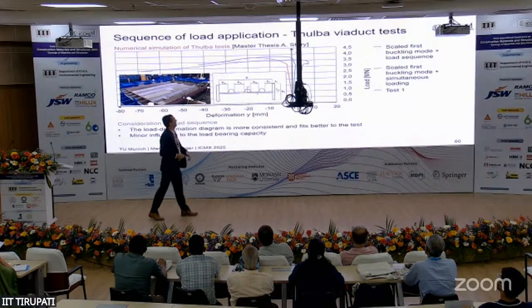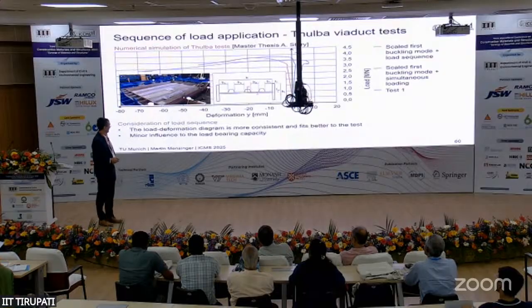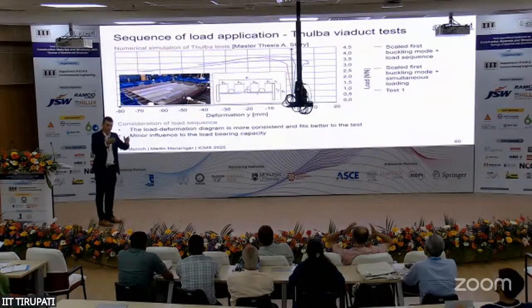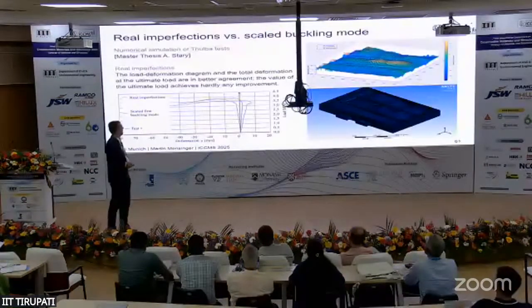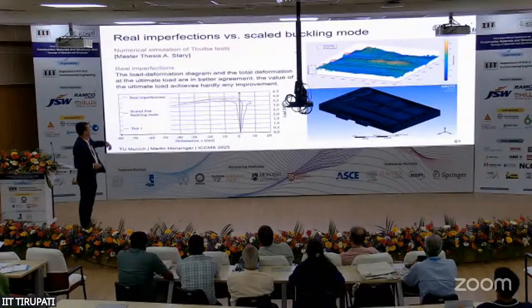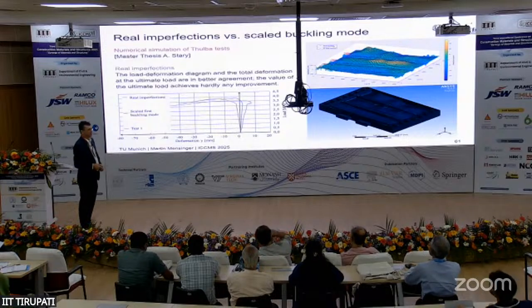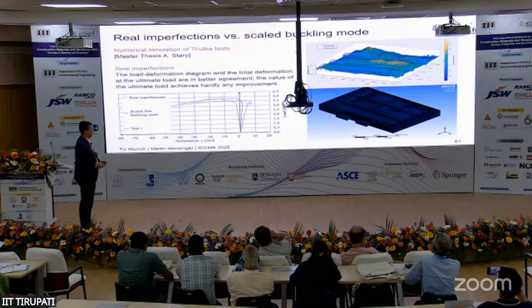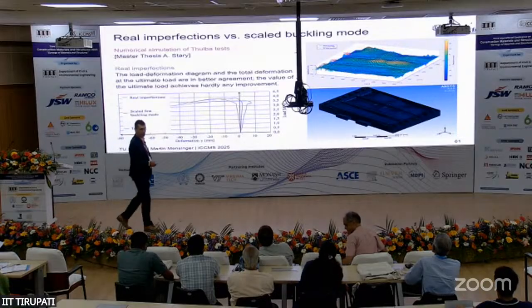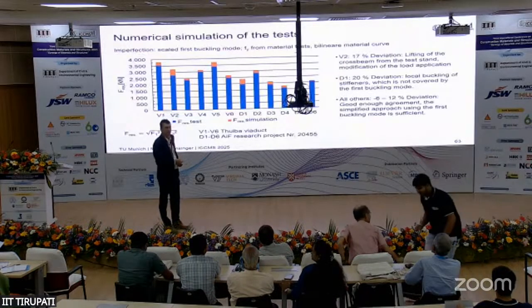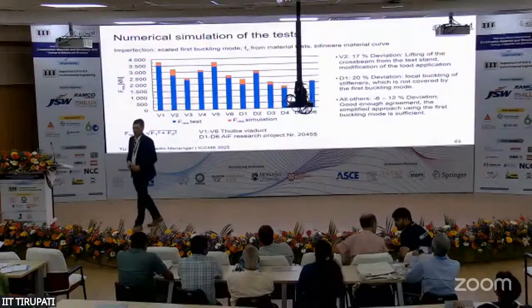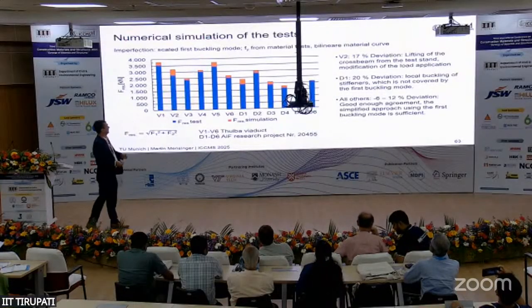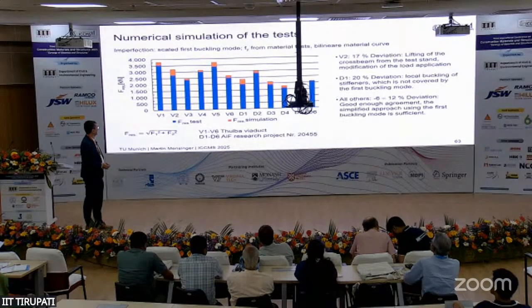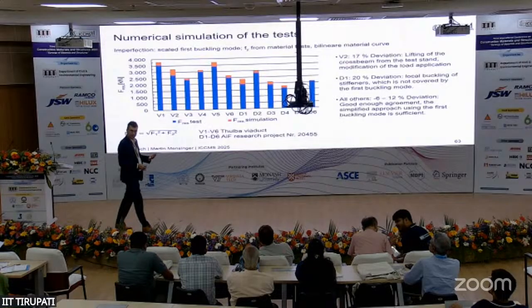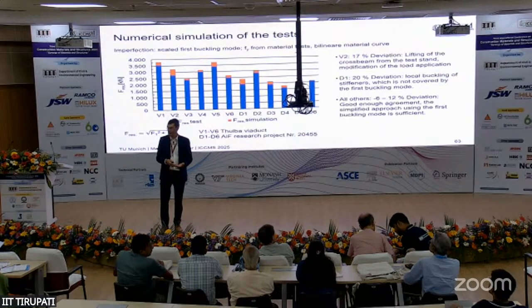And by considering the load sequence, it is possible to calculate this load-bearing behavior, but it's not necessary for calculating the ultimate load. And again, using the measured imperfections from laser scanning will just lead to more or less the same result. So also using the first buckling mode is a good approach, also compared to our measured results. And what we found out in all our calculations is that we slightly overestimated the load-bearing capacity compared to the tests with our numerical calculations.